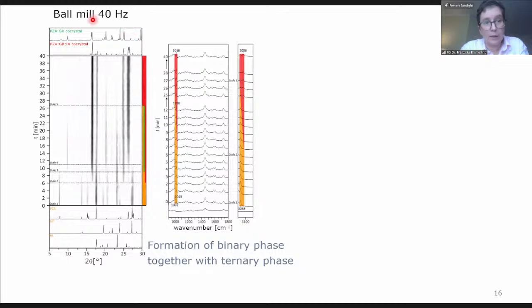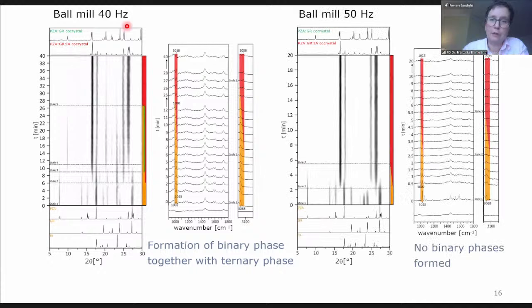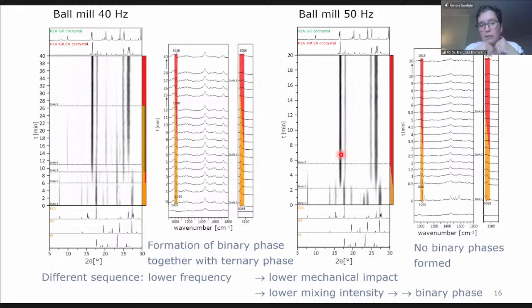Okay, if we change our milling frequency from the 40 hertz we used here to 50 hertz, you can see that the picture changes. So we no longer observe this binary compound, the green one, but we have a direct conversion of our starting materials to the final product. So what's happening here? If you think about it, with a lower frequency, we have lower mixing possibility. And also, if the starting materials get consumed, there is, let's say, less probability that three partners would meet to form a new compound. And therefore, we assume that we have in between the formation of the binary product, which is not necessary for the formation of the ternary one, as we can see in the higher frequency example, because this one is going directly to completion without this binary step.